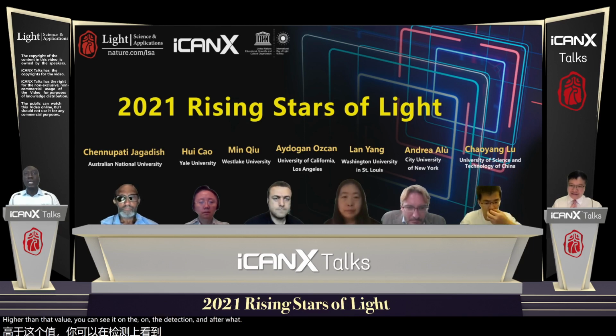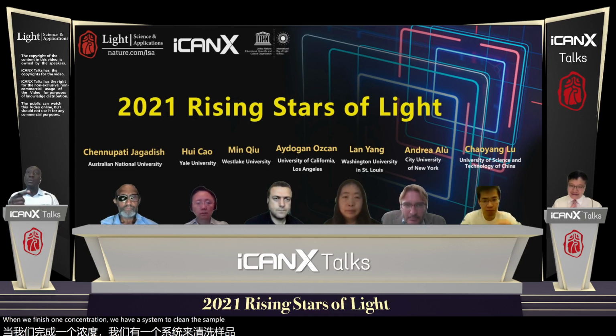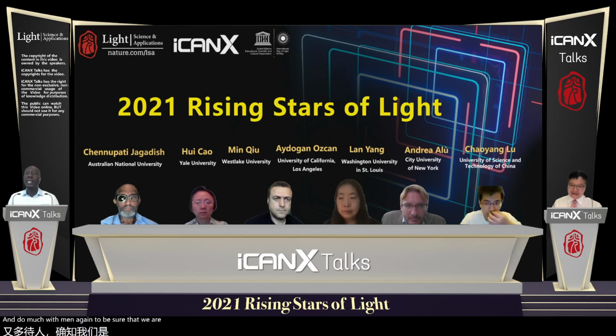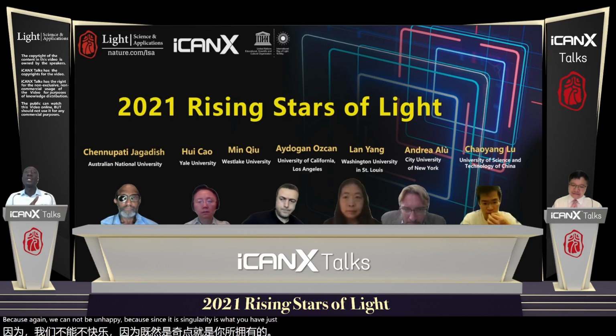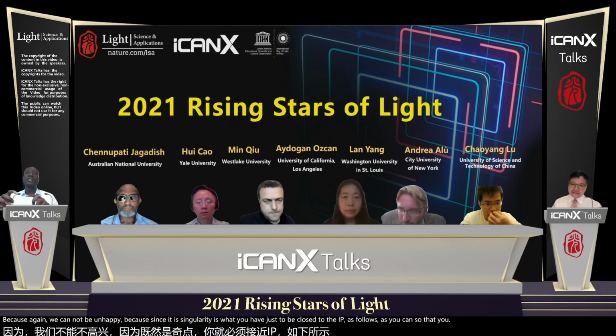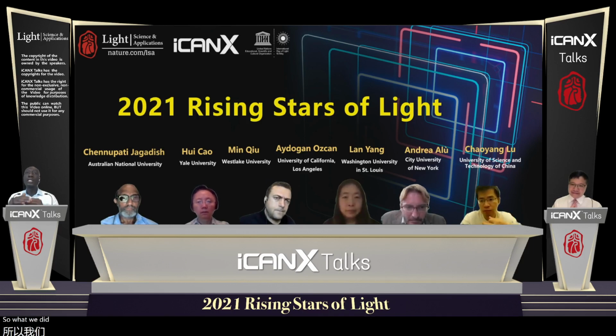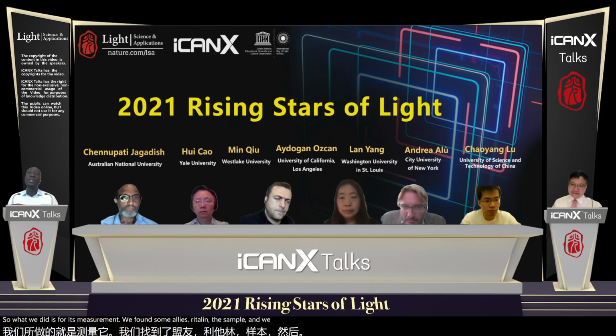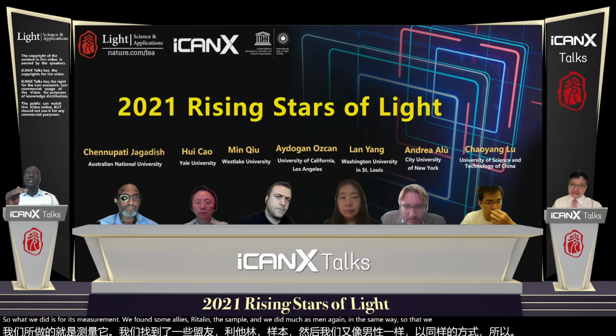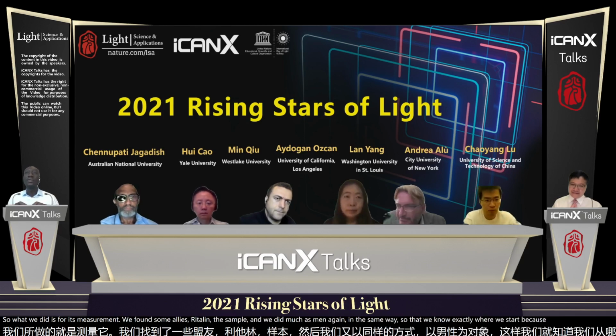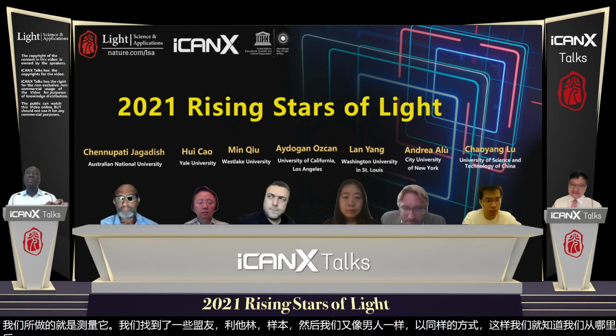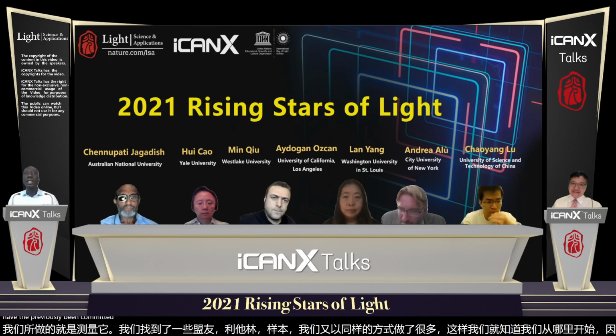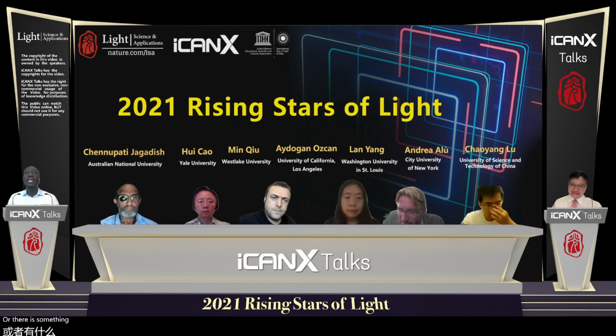And after what we did is, when we finish one concentration, we have a system to clean the sample and do measurement again to be sure that we are at EP. Because again, we cannot be at EP since it is a singularity, but you have just to be close to the EP, as close as you can, so that you have highest efficiency. So for each measurement, we functionalized, we cleaned the sample, and we did measurement again in the same way, so that we know exactly where we start. Because if after functionalization and you clean your sample, you did the measurement, you don't have the previous result, which means either you damage your sample or there is something attached on your sample that you are sensing at the same time.